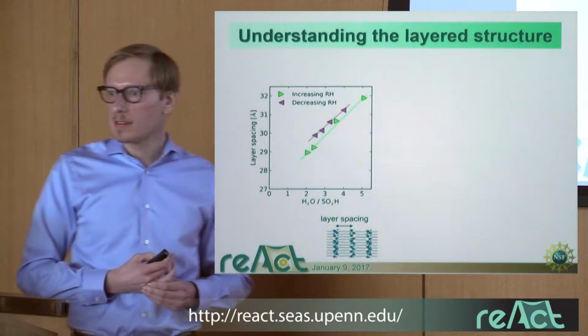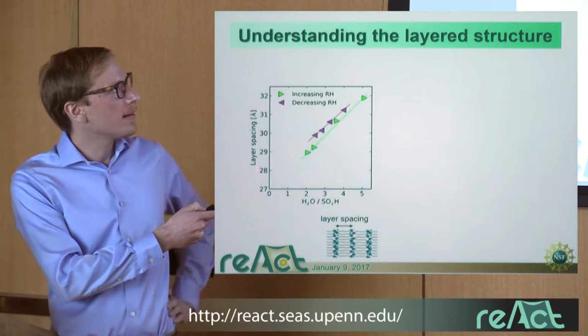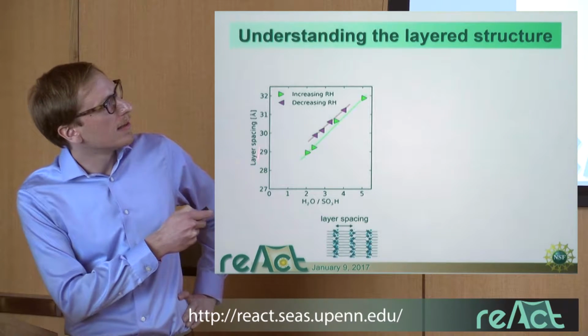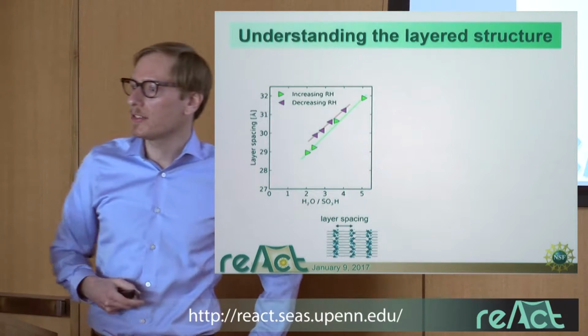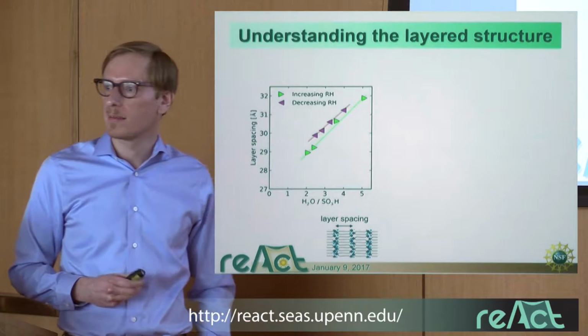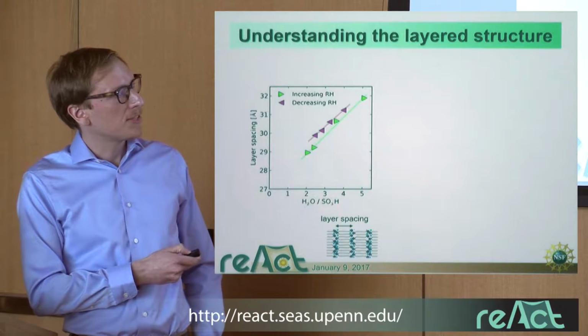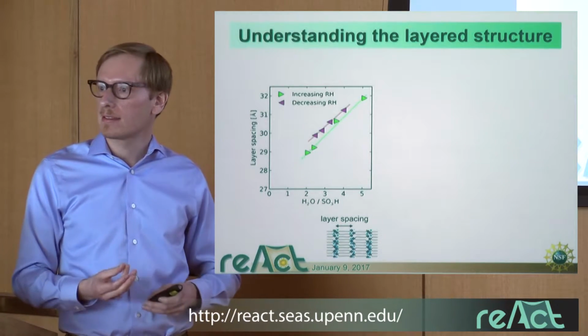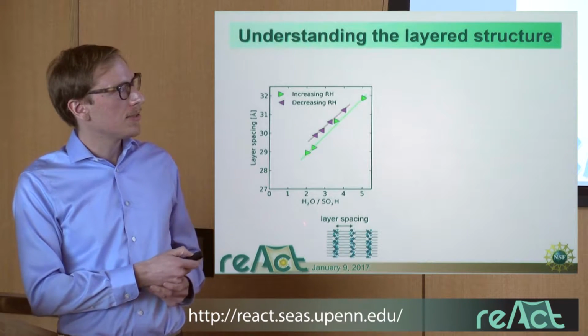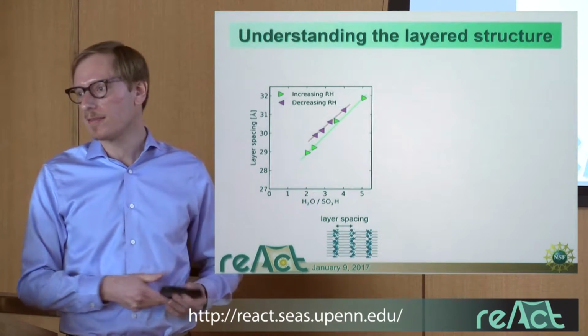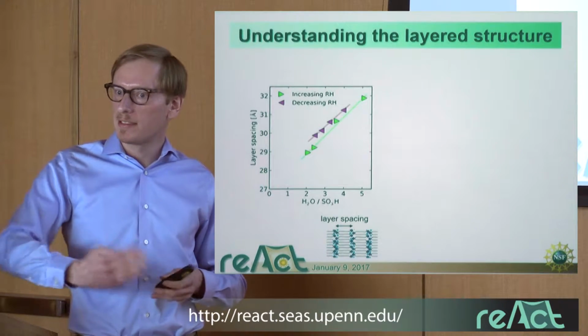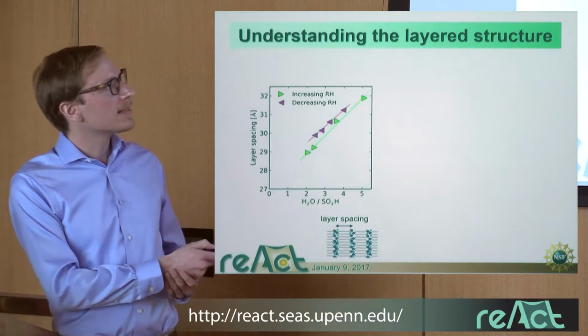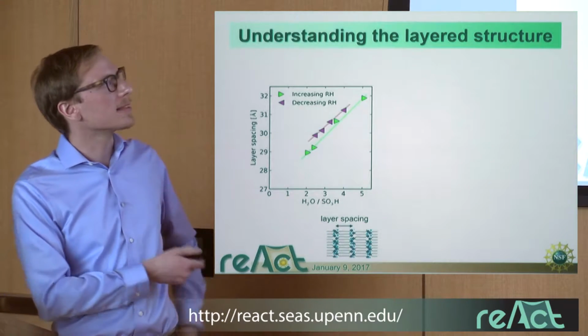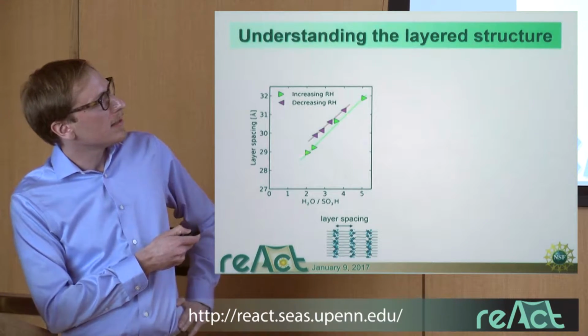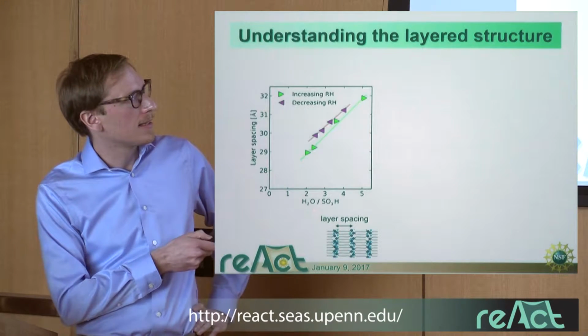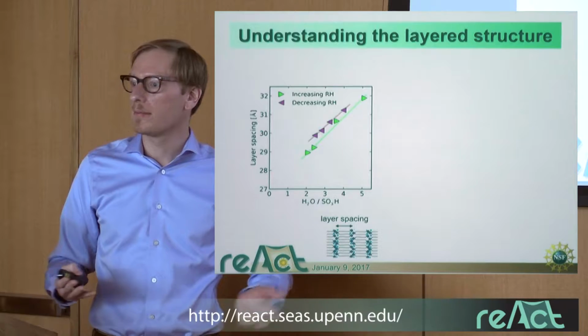Looking into this a little more closely, I've plotted here the layer spacing obtained from X-ray scattering. And I've also obtained the hydration number, also from experiments done at Grenoble this summer, where by changing the humidity, we're basically measuring the mass of the membrane as a function of humidity to obtain the number of water molecules per sulfonic acid group at each particular humidity. And so with those two data sets, I can combine them and make this plot where you see a linear dependence of the layer spacing on the number of water molecules, which makes sense for a lamellar structure.